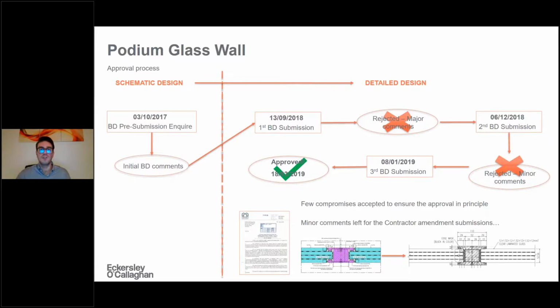So we started then with a first BD submission in September 2018, which was rejected with major comments, also depending on the fact that at that time the glass code in Hong Kong switched from one to another, so there were some slightly different requirements for the glass analysis. So then we had to resubmit in December of 2018 as well, and this submission was rejected, but with very minor comments. They were addressed in January, straight one month after, and finally everything was approved by March 2019.